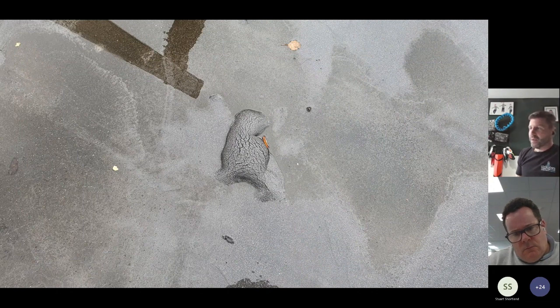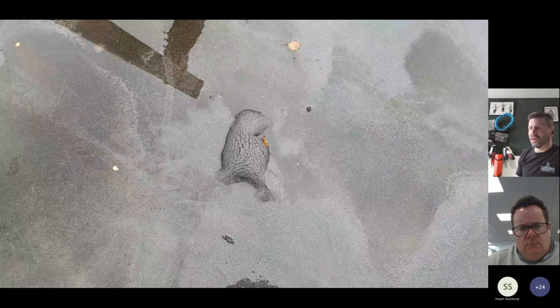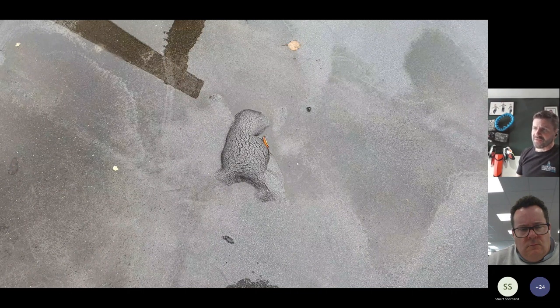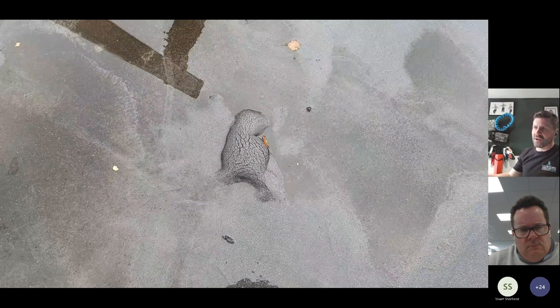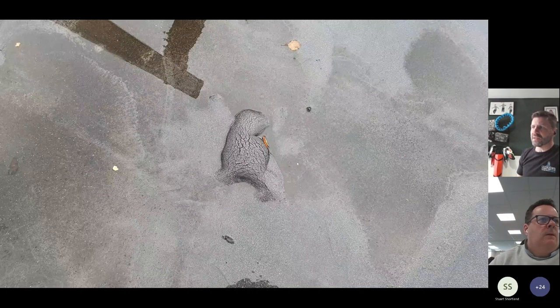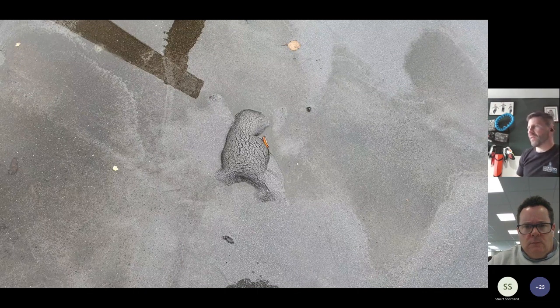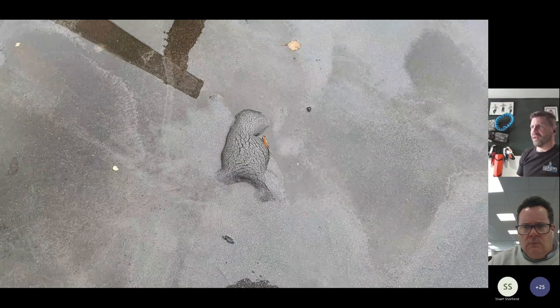Blistering, again, in asphalt is caused by a buildup of moisture underneath, as with any kind of blister. And again, that can be down to interstitial condensation. It can be down to moisture within the substrate. It can be down to when the asphalt is installed. It's installed in 2 coats. So if that first coat is not completely dry when the second coat goes over the top, then that will form blisters. Cement dust as well from the buckets, when they actually install it, can cause pockets in the asphalt, and they can expand and cause the asphalt to blow.